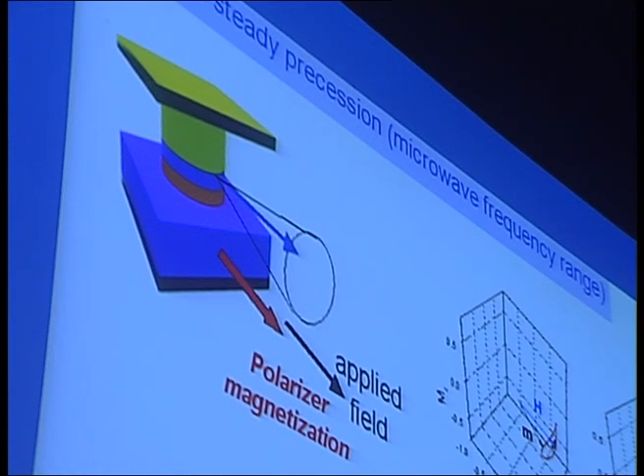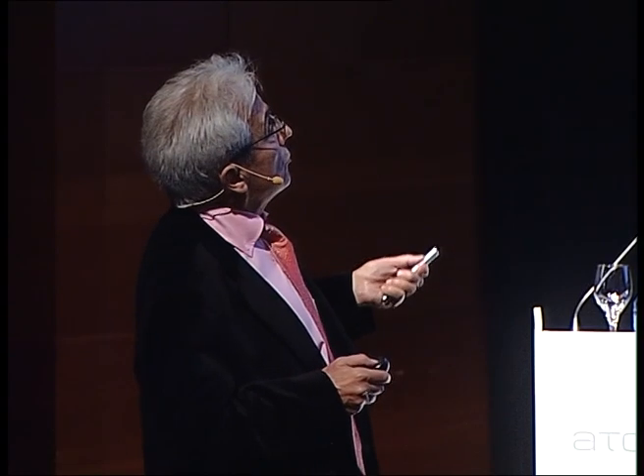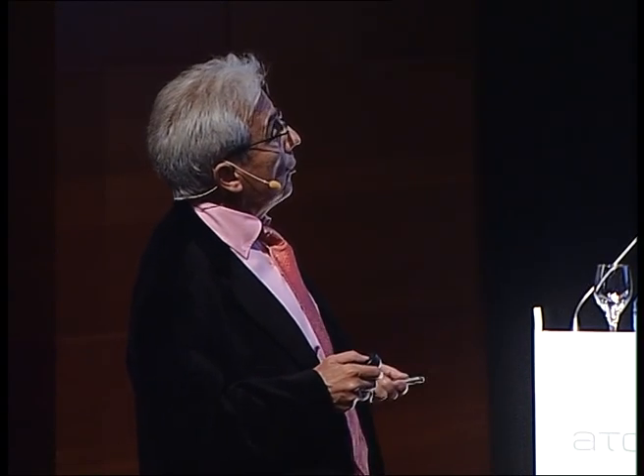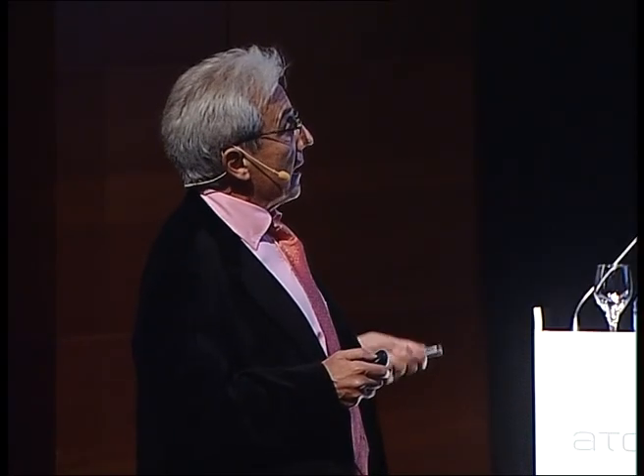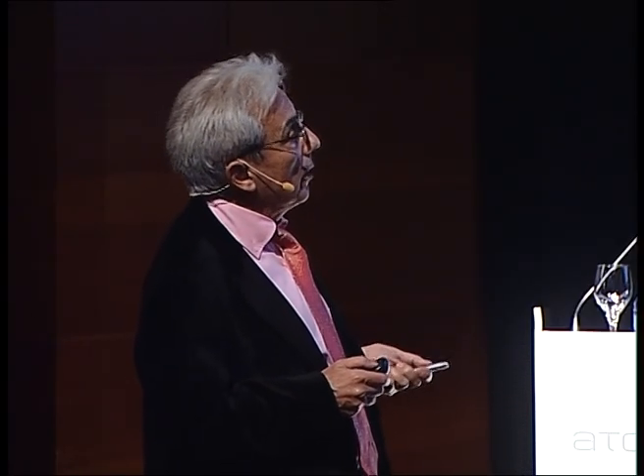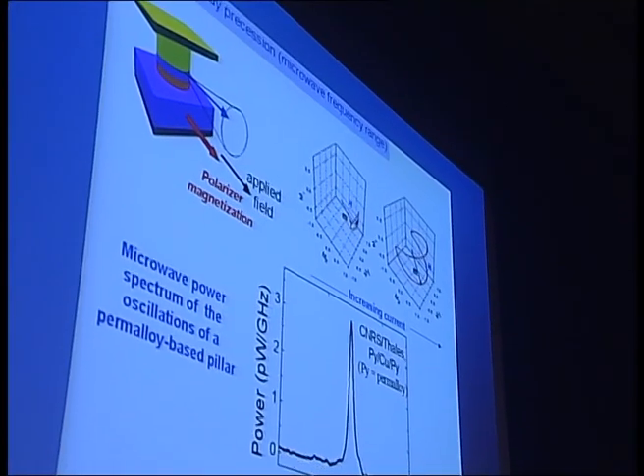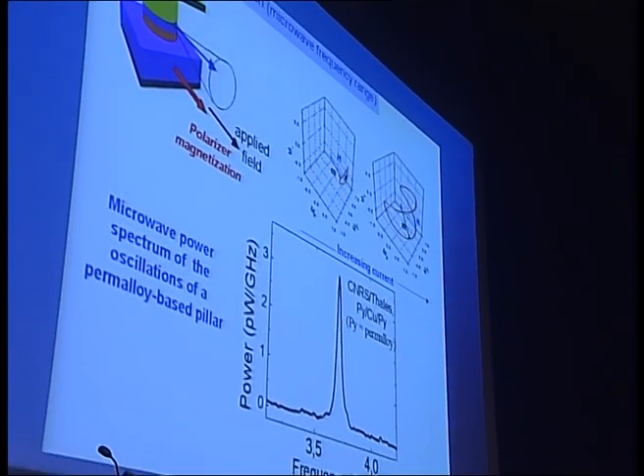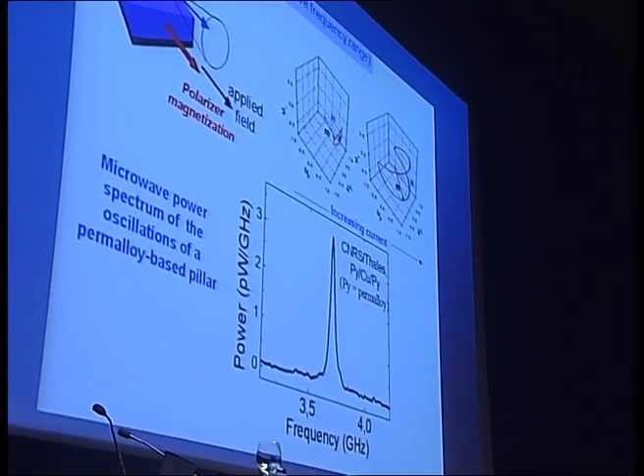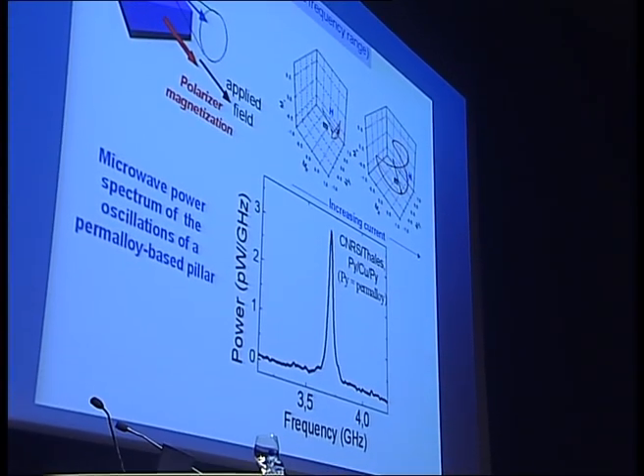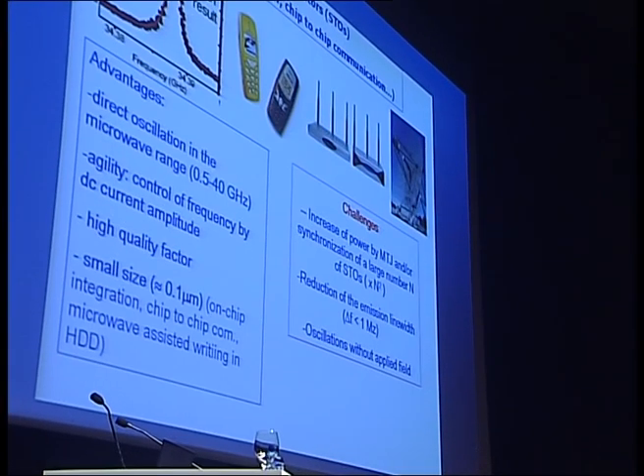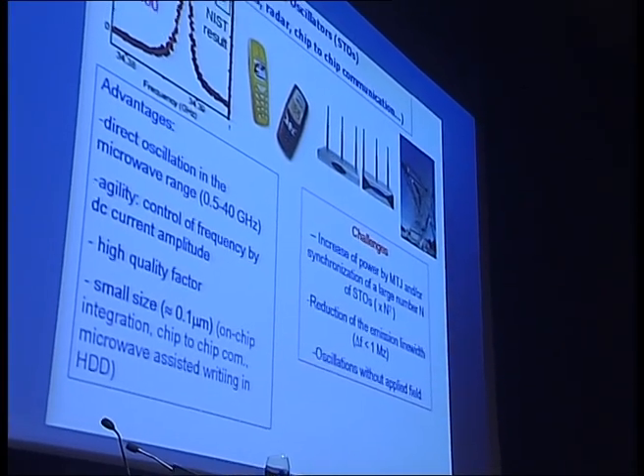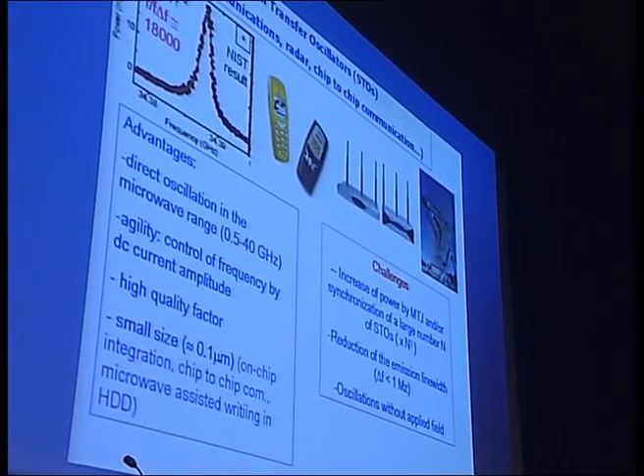If one looks with a spectrum analyzer at the voltage between the top and the bottom, one sees an AC signal, a microwave power with this line, this spectrum of microwave power, and so generation of microwave oscillation in the range of the gigahertz. Several interesting applications to telecommunication can be considered.